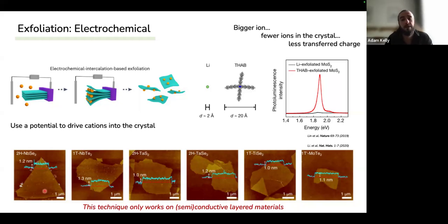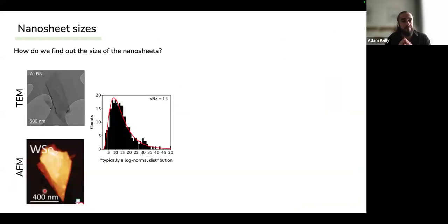monolayers that you get with this method, the nanosheets are huge, they're much, much bigger. The monolayers are huge, far bigger than we get with liquid phase exfoliation. So I've mentioned these nanosheet sizes. How do we find out about the size of the sheets? Well, TEM and AFM statistics are usually the way you do it.